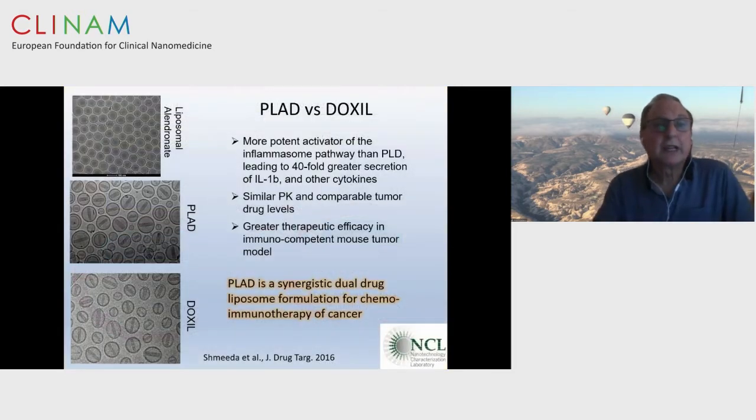This is how the liposomes look before encapsulation of doxorubicin and after encapsulation of doxorubicin. You can see the rods, due to the precipitation of the alendronate doxorubicin salt, which look pretty similar to the Doxil rods. The only difference is that our liposomes tend to be more round, and the Doxil liposomes are more oval-like. This probably has to do with the fact that the rods of Doxil grow a lot, and by themselves push and elongate the liposome, creating these funny shapes.